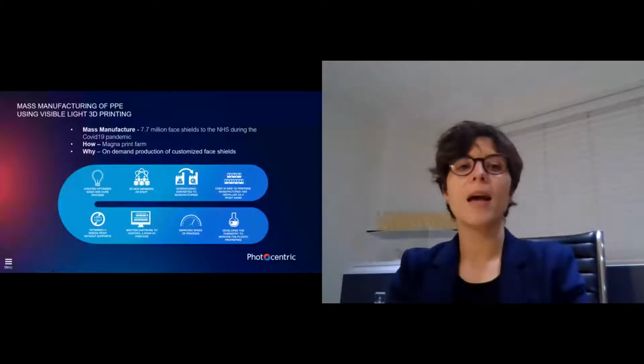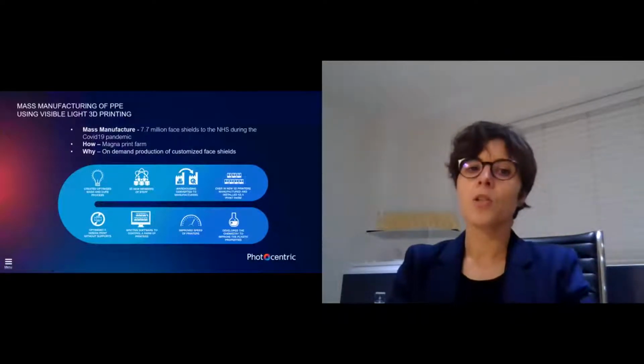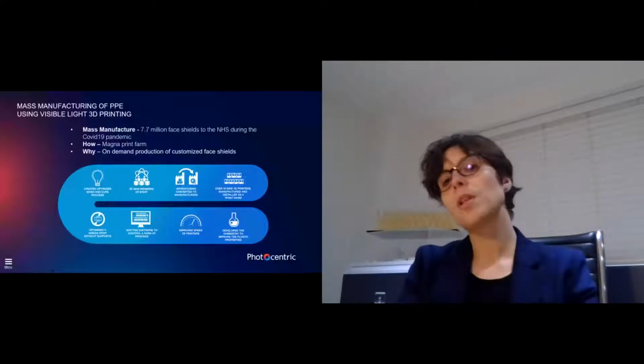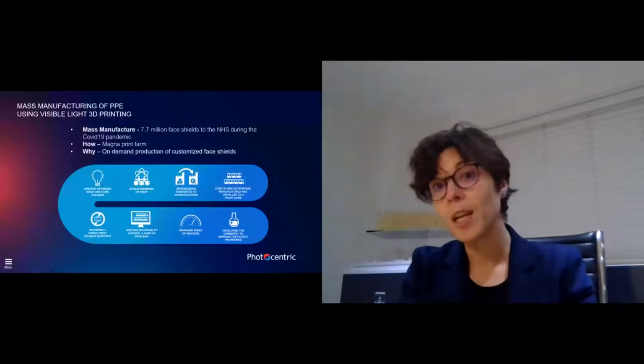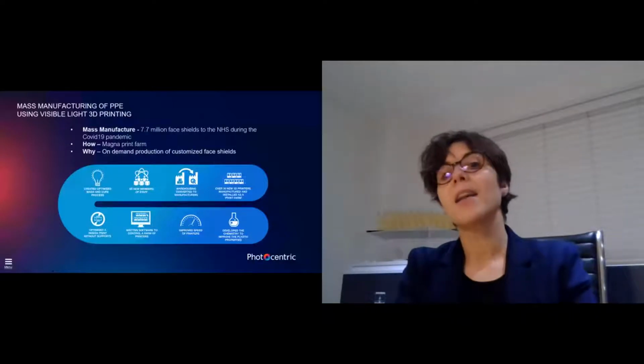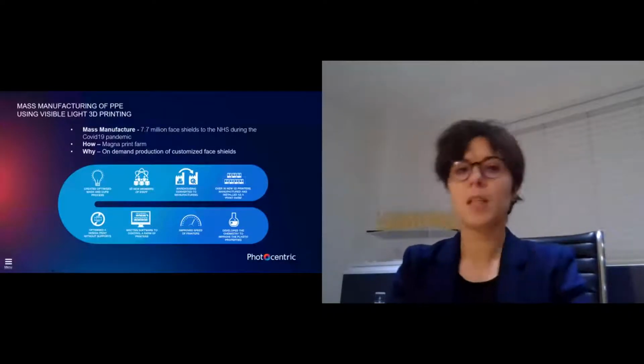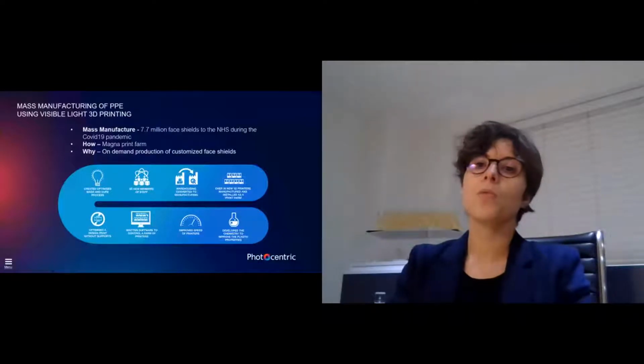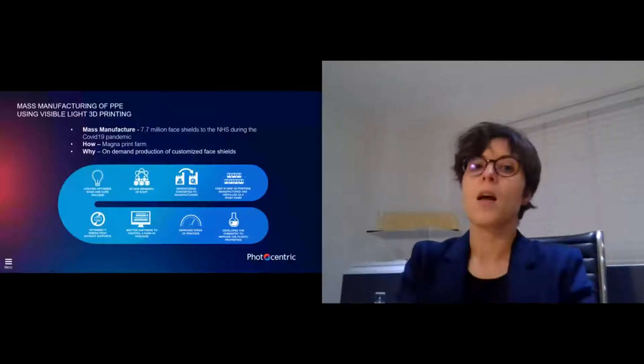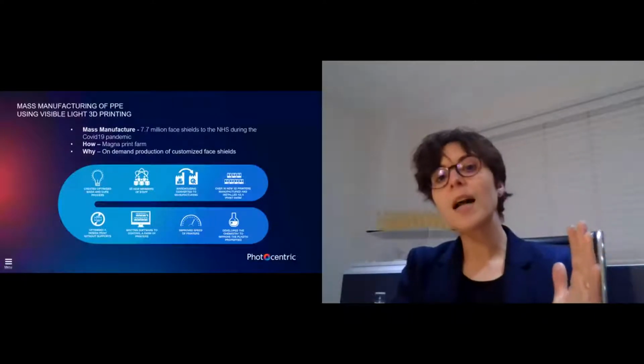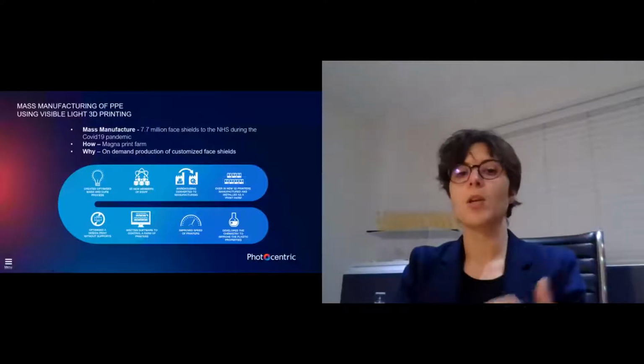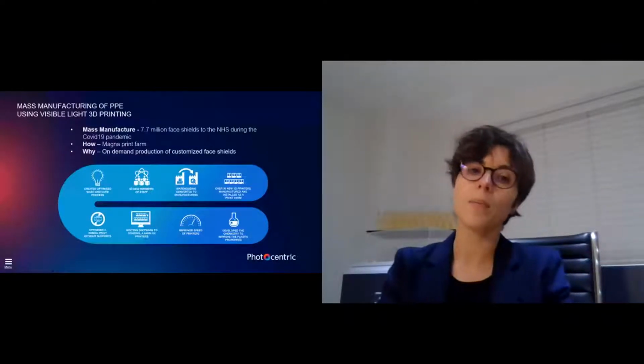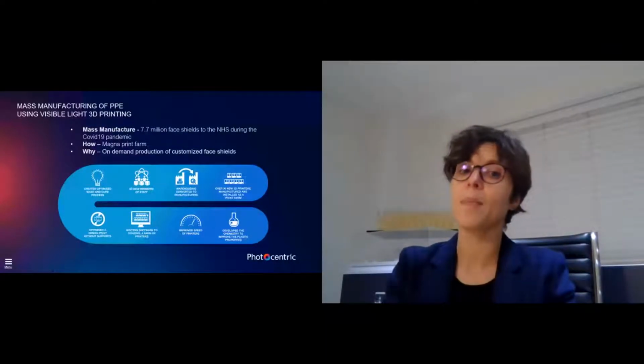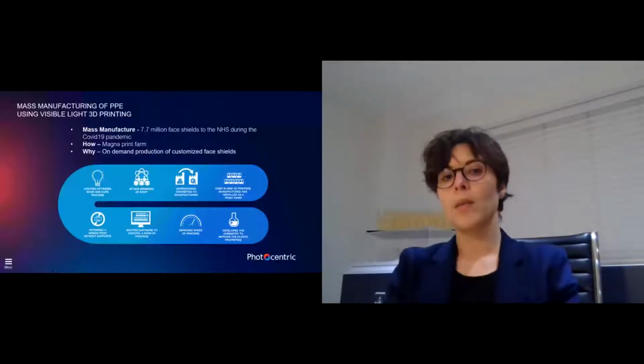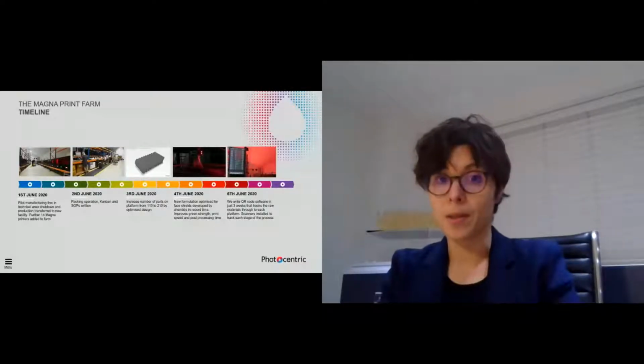So we worked on the one hand on the design of the PPE. At the beginning, we had a design which was not really optimized for 3D printing. And we used design for additive manufacturing to reduce the amount of materials in our design, to reduce the amount of support, so to create a supportless STL file, and also to stack as many of them on the platform as possible. So we went from 100 parts on a platform to 210 parts with the optimized design. So within 3 hours, you had 210 parts.